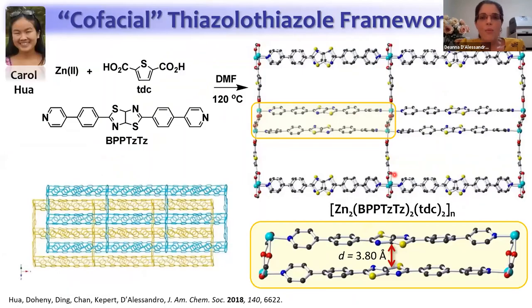So here's one of our first materials using this type of design, and it's based on thiazolo-thiazole ligand. Well, you'll notice that in the framework itself, we have these cofacial thiazolo-thiazole ligands. They're within pi stacking distance, 3.8 angstroms, and the material is interdigitated, if you like. So it doesn't leave very much pore space. But interestingly, this cofacial arrangement is a little bit like double glazed windows in a home.